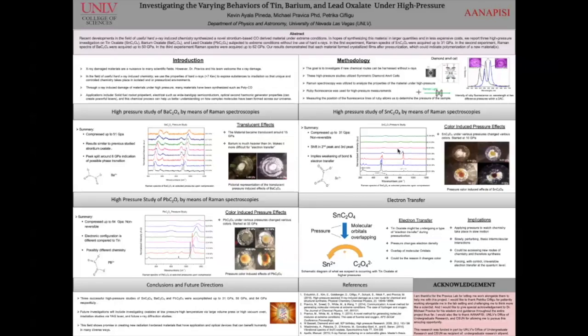Now, for the tin oxalate, I went up to 31 GPa, and what happened is that as I increased pressure, the second and third peak started shifting to the right and left respectively. And this could imply a weakening of a bond or even an electron transfer, which I will talk more about in a bit. Lastly, there was this qualitative, interesting behavior of the material, where it changed from a white to an orange to a red to a really dark red. And as we decreased pressure, it stayed in this kind of golden yellow color. And of course, this could be explained by this electron transfer I'm talking about.